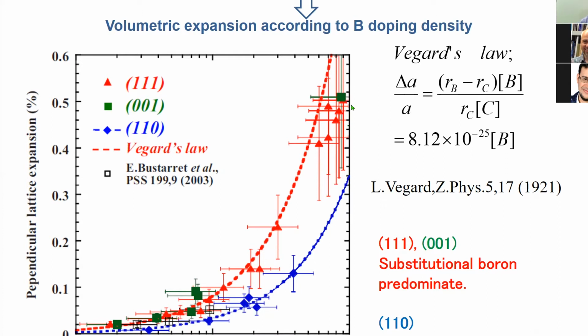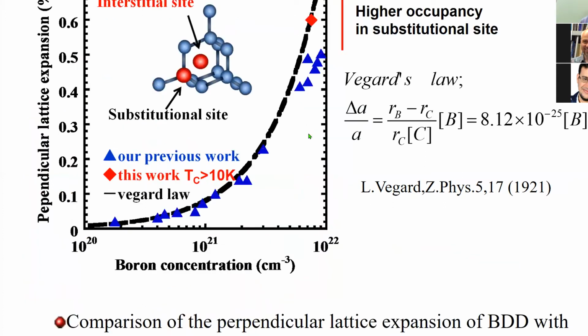TC is high in these regions, and then we get very high expansion in the particle. These expansions, according to the boron concentrations, show some tendencies, and in some cases the substitution site cannot be occupied, only the interstitial site.